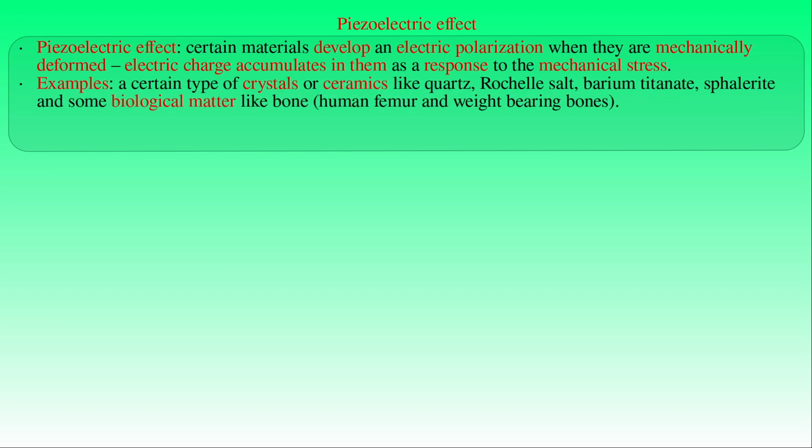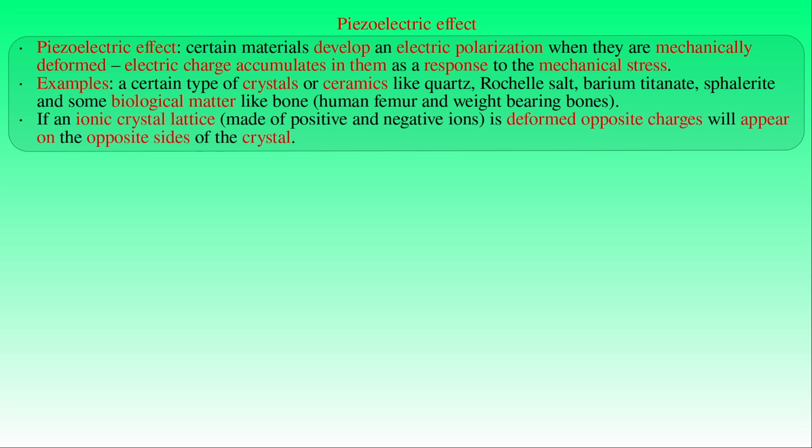Besides crystals, this effect has been observed in certain types of ceramics and biological matter like bone, for example human femur and weight-bearing bones. The typical examples for crystals and ceramics that can produce piezoelectricity are quartz, Rochelle salt, barium titanate, and sphalerite. Ionic crystals consisting of positive and negative ions arranged in a repeating, highly ordered three-dimensional lattice can have piezoelectric properties. If such a crystal lattice is deformed under the influence of external forces, then opposite charges will appear on the opposite faces of the crystal.